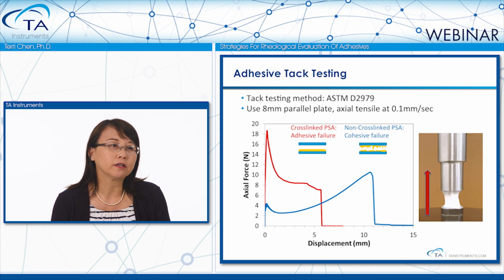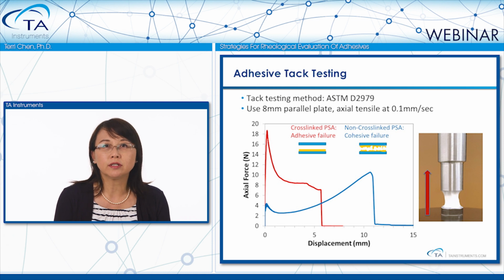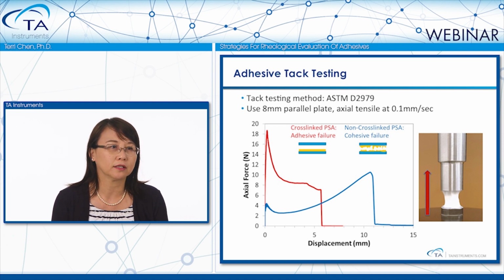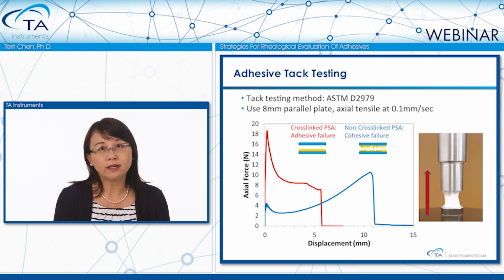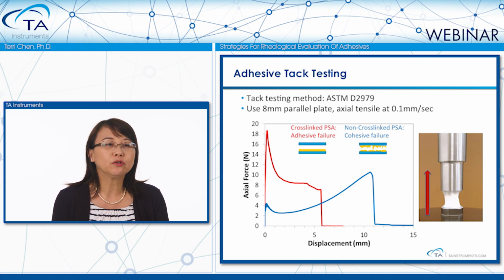This following figure shows the tack testing results of a non-cross-linked and a cross-linked PSA sample. The cross-linked PSA shows significantly higher cohesion strength due to the introduction of a cross-linking network. Therefore, failure occurred at the interface. The non-cross-linked PSA, however, has weaker cohesion bond, so failure was observed to be between the adhesive polymer layers.